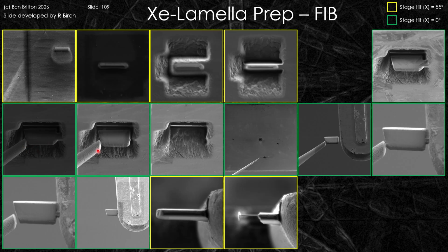We can see the welding process is sticking. We can then see that we've lifted this out the way. The lamella is no longer located in the sample, it's on the end of the needle, and then the needle is brought towards the copper post, and then it's welded into place. You can see this is the back weld that's presented, and then we do the thinning process as we saw beforehand.